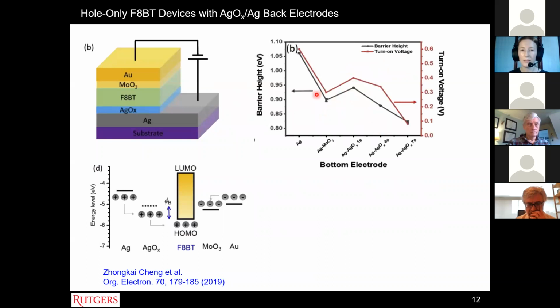And also consistent with those IV curves, we saw that the barrier height was lowest for the 7-second case, as well as the turn on voltage being lower in general for the silver oxides compared to the silver. However, overall, the current density was best for the 1-second case, again probably due to lower series resistance compared to the other two.